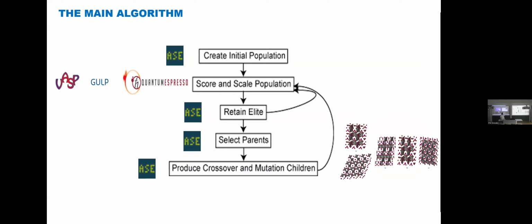So this is our algorithm. We use ASE to create an initial population of the structures. Then we use some calculators. We use GULP here, but potentially we can use VASP and Quantum Espresso. But we made it on a computer in Kyiv Academic University, not on a supercluster. So we used Gauss just to boost the time of our calculations. Then we calculate energy with GULP. Then we also use ASE to take the best structures, to mutate them with some algorithms, and then we repeat this algorithm till we find some interesting structures.